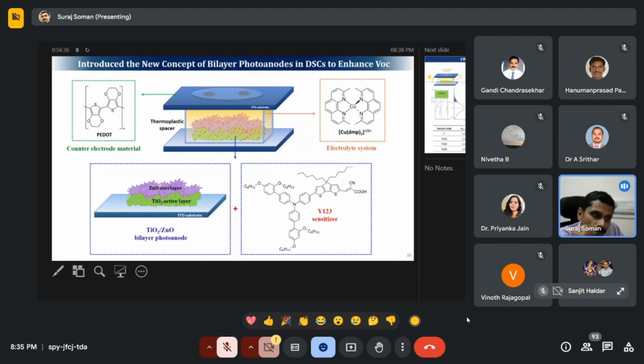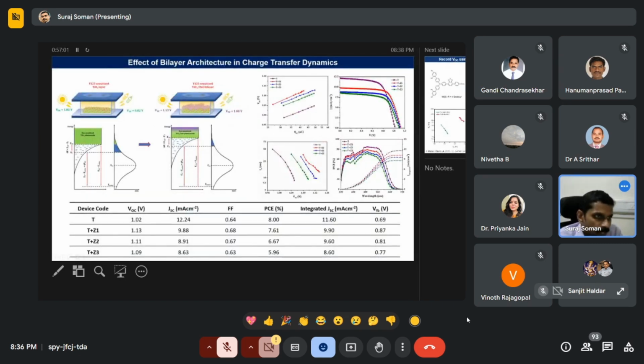Then interestingly, what we have seen is a very huge, drastic drop in performance because zinc oxide is more acidic. It creates certain issues with the dye desorption and all. But we have seen a huge improvement in the voltage. There was a huge improvement in voltage. And then we went back and understood that we forgot to remove the zinc oxide layer. And then we explored it in further detail.